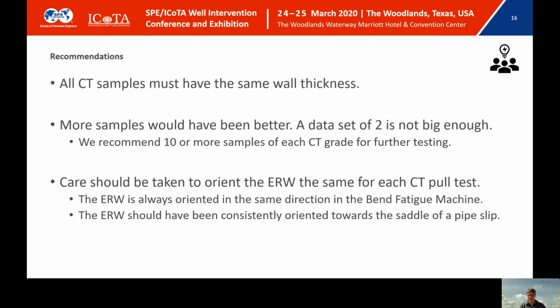And one thing that we didn't do and sort of regretted as we were writing the manuscript is that, when you do bend fatigue testing, you always orient the ERW, so the seam within the coil tubing, in a particular direction. And we didn't take care to do that when we did our slip testing. And perhaps had we done that, we might have seen a little bit more consistency in the data, because the slips would have been always oriented in the same direction when it was applied, or the slip marks would have been oriented the same on the samples when they were put in the bend fatigue machine. May or may not have had a difference. I kind of think it would have, but again, we don't have the data to back that up.